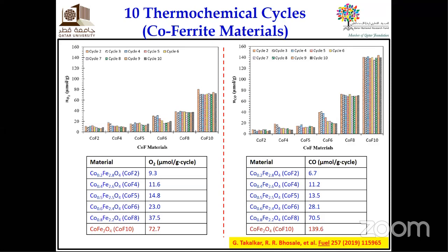Now, if I compare cobalt ferrite with nickel ferrite, they're almost identical. Only a slight difference is there, maybe because of experimental error, or maybe the cobalt ferrite is slightly better than nickel ferrite. So this is what we have observed in this case.